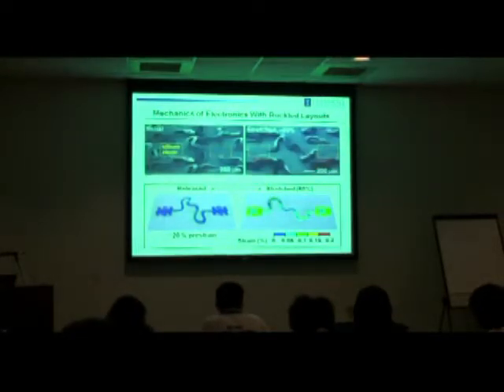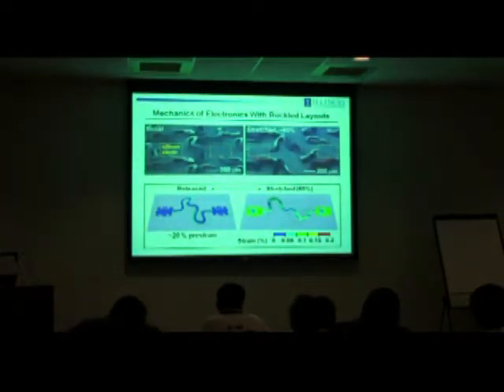So the concept then is to use this kind of idea, implement a circuit in which your active devices are in the islands, and then these non-coplanar bridge structures support the interconnect. Okay? So this is an example just in silicon. You can see with those two ideas, you can really accommodate very large strains with a completely linear, elastic response of the overall system. So these things can stretch 100, 200%, much more like a rubber band. So those are the ideas just implemented in a sheet of silicon. As I mentioned, you can use those concepts and extensions of them to build silicon electronics. And here's an example of that.